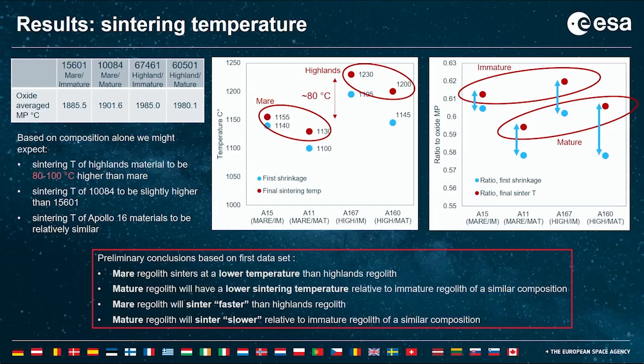So some preliminary conclusions based on this first data set is Mare regolith sinters at a lower temperature than Highland regolith. The mature regolith will have a lower sintering temperature relative to immature regolith of a similar composition. Mare regolith will sinter faster than Highland's regolith, and mature regolith will sinter slower relative to immature regolith.